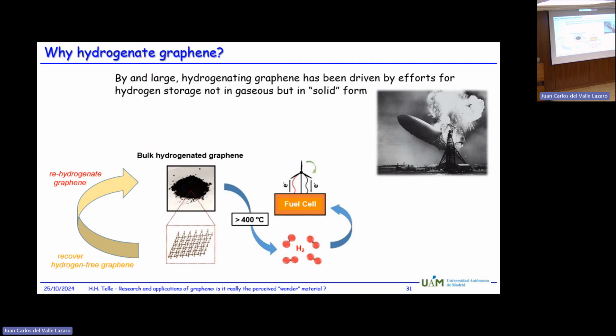And also, you find that using graphene for this type of storage, you can bind the hydrogen to the graphene, and you can extract the hydrogen again by heating it up. You get hydrogen, which you can then inject into the fuel cell. Once all the hydrogen is gone, you take your graphene back into the system and rehydrogenate it. So it is a method where you do not have a once-off, but you can recycle the thing over and over again. Again, this has been demonstrated to work, but so far only on a small scale.